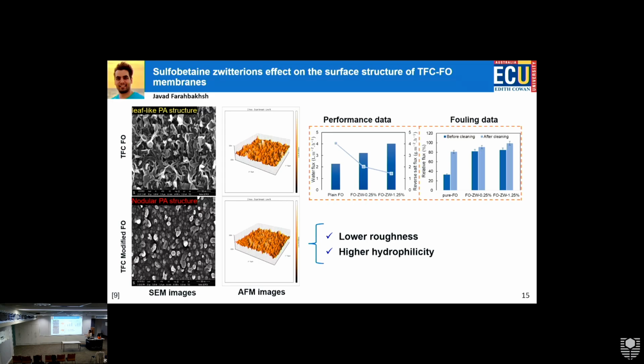So in this one, I go through studies that Javad has done. He has added sulfobetaine zwitterions. Zwitterions are materials that have both negative and positive charges, so they have more balanced charge, but they are highly hydrophilic. If we add them to membranes, they have been known to increase the hydrophilicity significantly, and thereby enhance the efficiency against fouling, as well as the permeability.